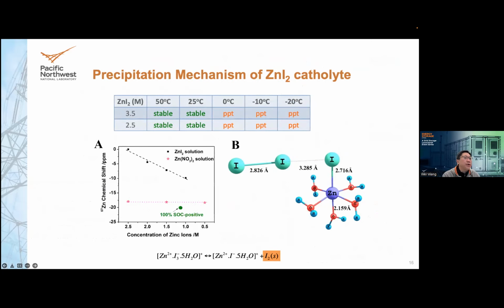But this system has a problem, opposite to the vanadium system. It precipitates out at lower temperature. And the exact reason is because the triiodide is pretty happy in the water until it has a cation move closer to it.